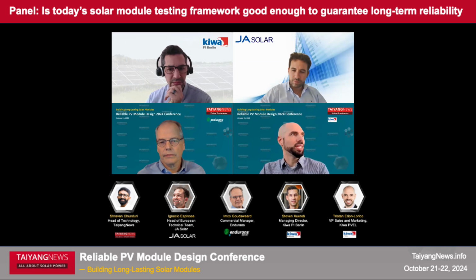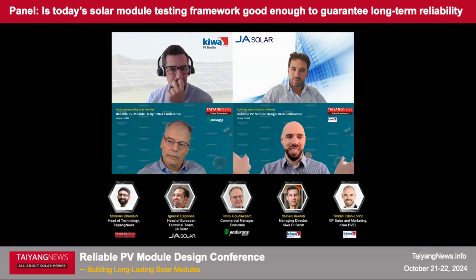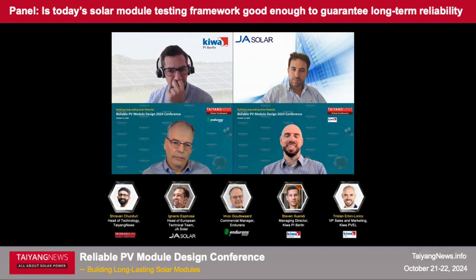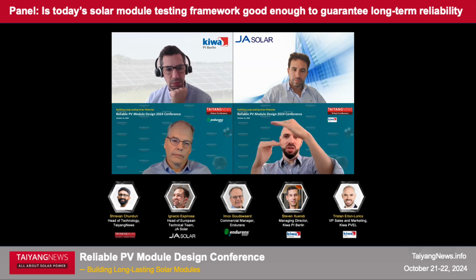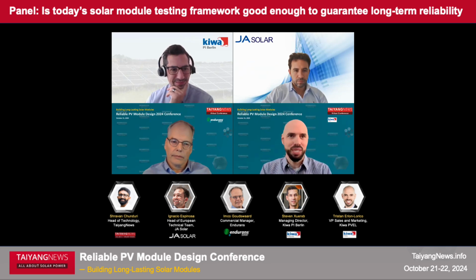Well, I think we see a trend across, generalizing. We do multiple tests. We test multiple cell and module technologies. We have glass backsheet, glass-glass, and multiple tests by multiple manufacturers. So it's somewhat difficult to boil all that down to one trend. I think generally, though, we are seeing that reliability is improving. If you look at our thermal cycling or damp heat results or PID results, 10 years ago, the range of results was much wider. And that has slowly gotten better over time. It's certain that multi-busbar modules are more reliable than 3-busbar. And we're seeing more reliable backsheets come on the market. Shout out to Endurans and other manufacturers making those, as well as better encapsulants, etc.